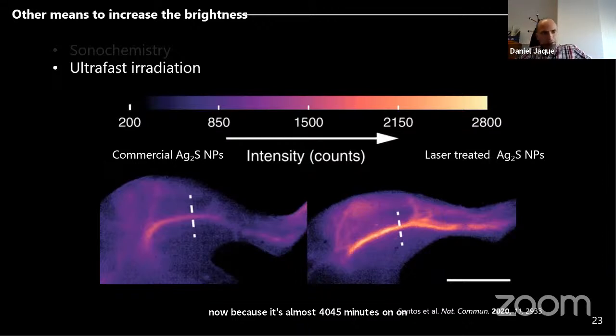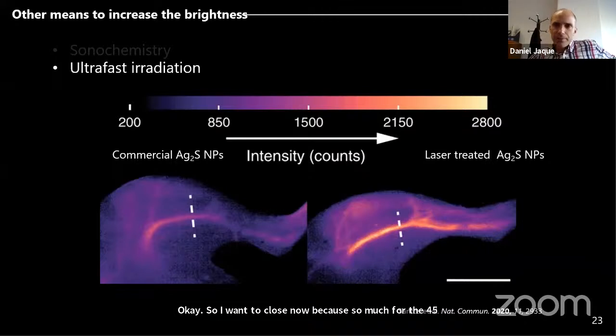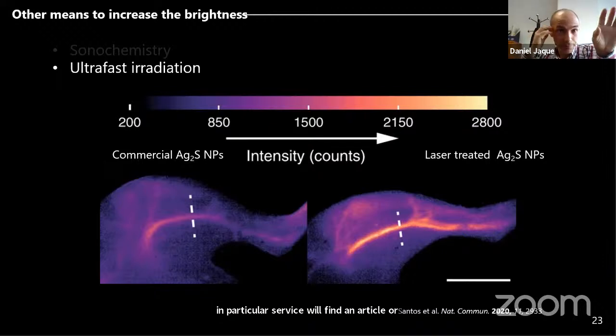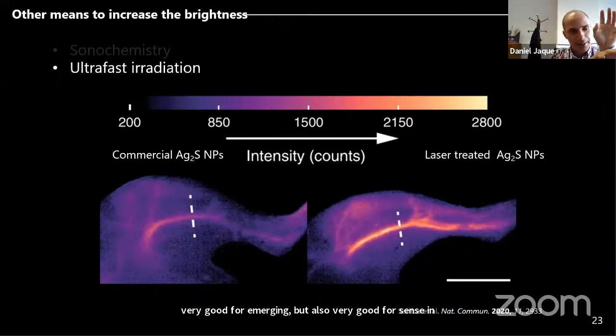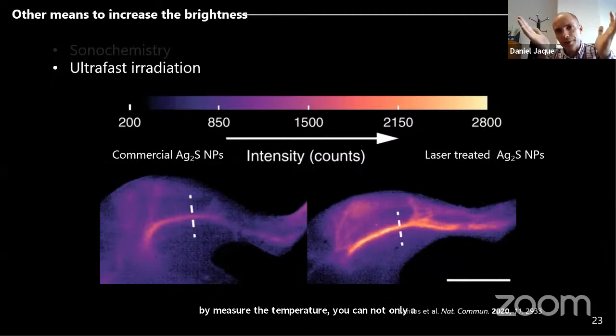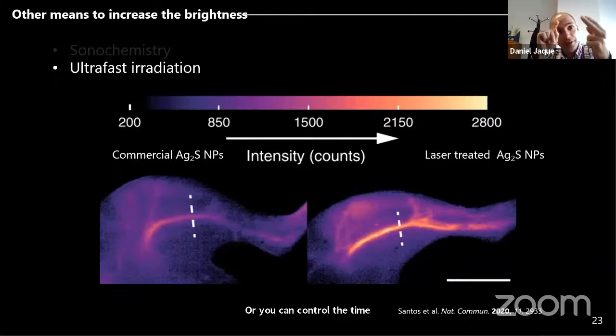The conclusion of this work is that silver sulfide, I mean, in general, infrared emitting nanoparticles are a super interesting system for bioimaging because you can penetrate in the tissues. In particular, silver sulfide nanoparticles are very good for imaging, but also very good for sensing, in particular for temperature sensing. And the idea is that you are not measuring the temperature just because you want to measure the temperature, but because you want to control the temperature of a tumor, or you can use the temperature of the liver for diagnosis, and so on.